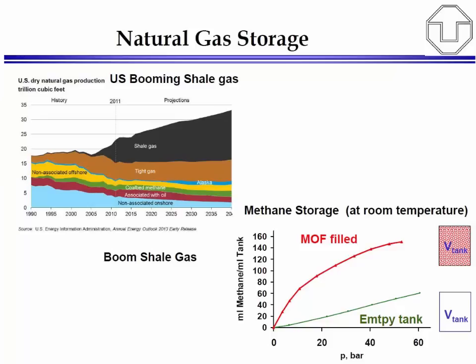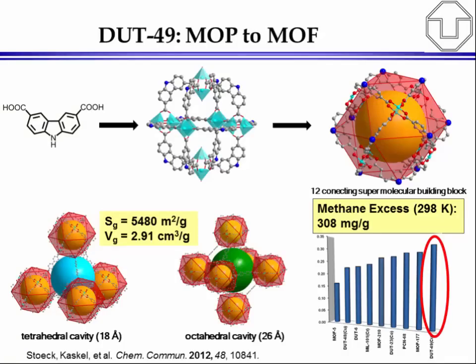And in the next slide, I show one example of a porous MOF, which is also synthesized in Dresden, DUT49. It is also synthesized from a metal organic polyhedron using, again, the square planar nodes connected by the carbazole linker, as you can see on the middle and the upper part of the slide. And these metal organic polyhedra are connected into a three-dimensional porous structure with very large pores up to 2.6 nanometer in diameter, almost 5,500 square meters per gram surface area, and this material is currently the